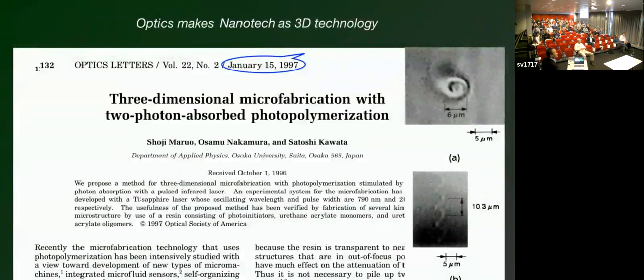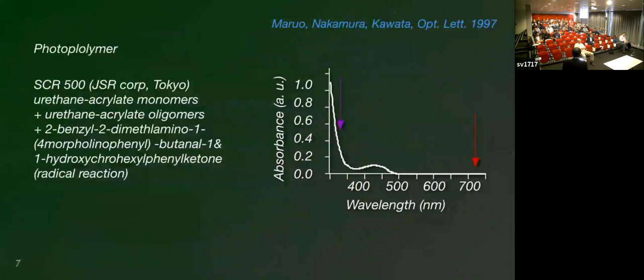So I wanted to do this. Some years after, I proposed three-dimensional microfabrication made by two-photon photopolymerization. We made 3D structures with two-photon femtosecond lasers in photo-polymerizable resin more than 20 years ago. We used a commercially available photopolymer which has an absorption in UV but is transparent to near-infrared. This polymer solidifies the resin if given UV light, but we wanted to use near-infrared.